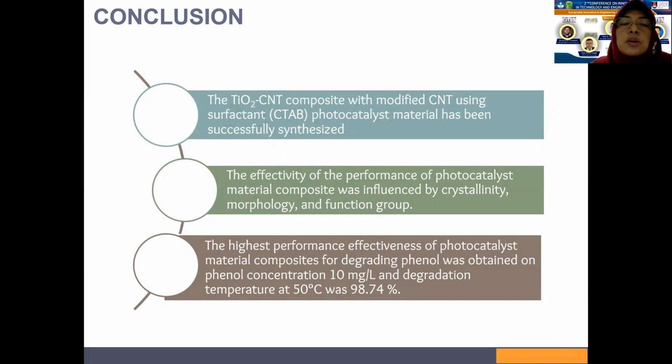The effectiveness of the performance of the photocatalyst composite was influenced by crystallinity, morphology, and functional group. The highest performance effectiveness of the photocatalyst composite for degrading phenol was obtained at a phenol concentration of 10 ppm and a degradation temperature of 50 degrees Celsius, which was 98.74%.